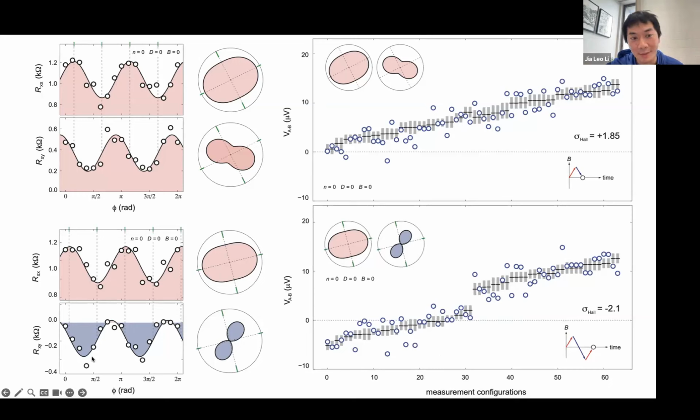Okay, all right. And the reason that such a big Hall conductivity gives rise to a relatively small Hall resistance, or is very far away from quantization, is because there is a longitudinal resistance, right? The sample is conductive, but we're just mapping out the direction of its conductivity matrix.